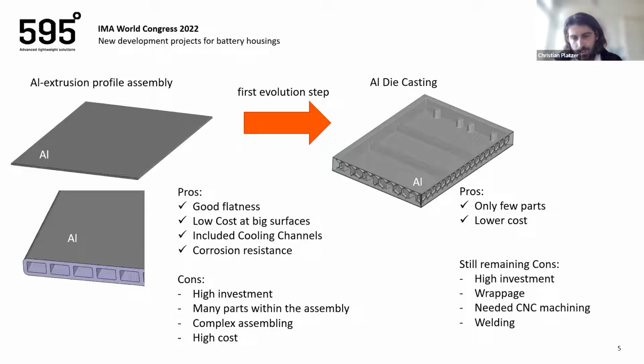And they like to use aluminum profiles because they fear corrosion, of course, from the housing with the coolant. And this is one of the main reasons why they don't want to use magnesium in battery housings. But there are also disadvantages in using those profiles. They assemble them from many, many different parts. Like we heard in the first presentation, this is basically the idea why you want to change to big castings, because you want to prevent assembly lines. And because they in total add up to quite high costs for the battery housings.